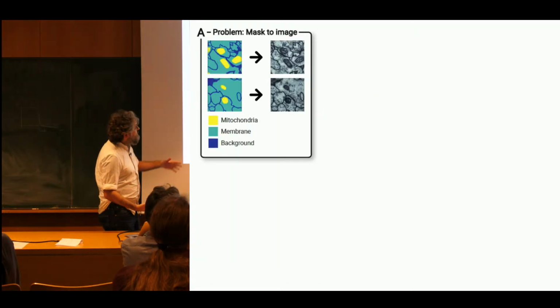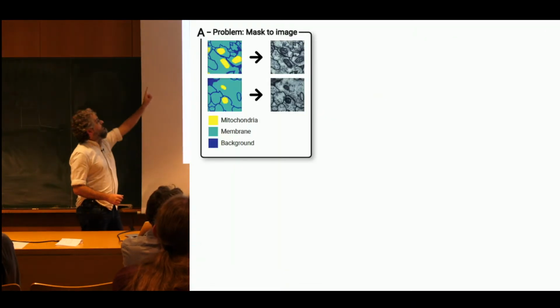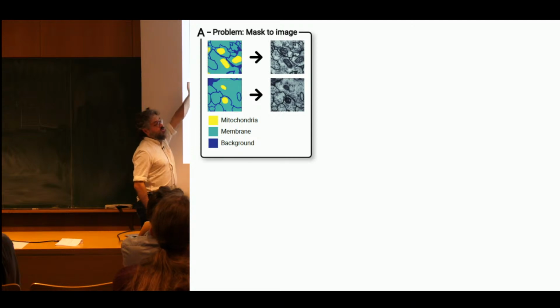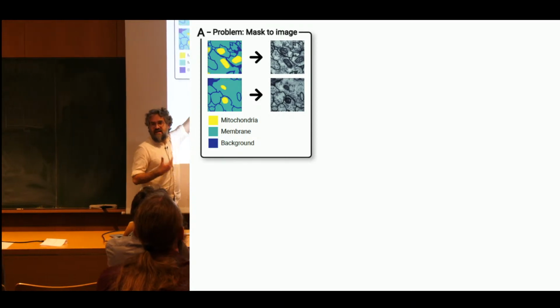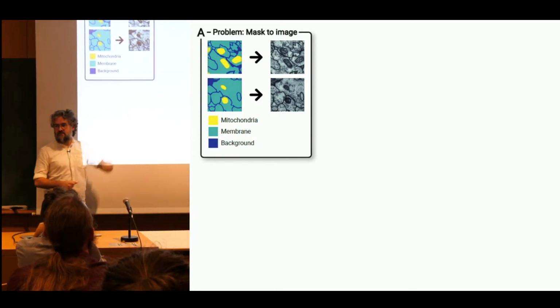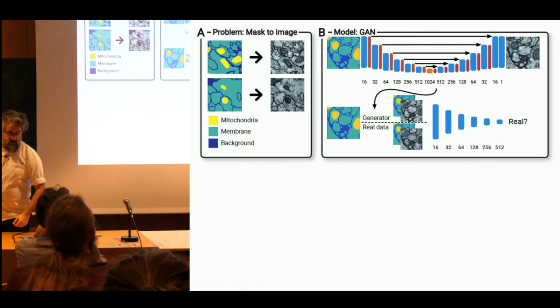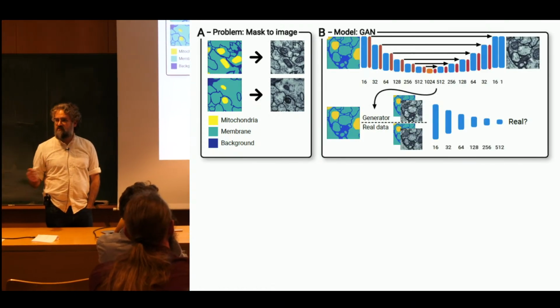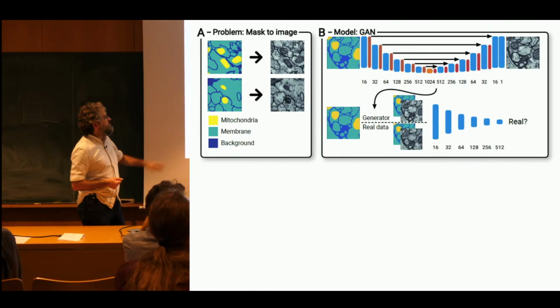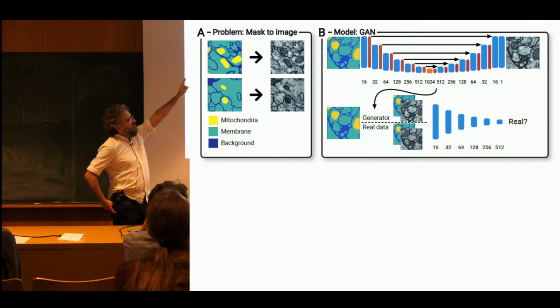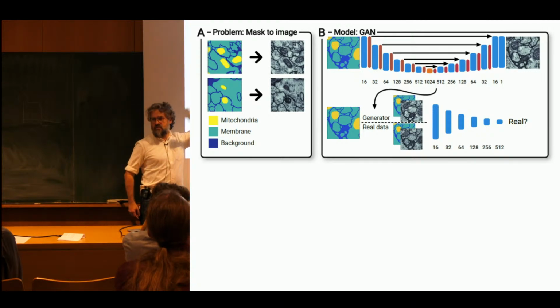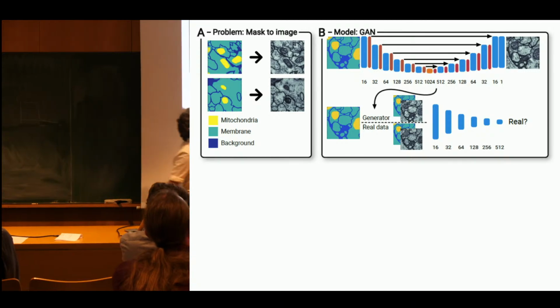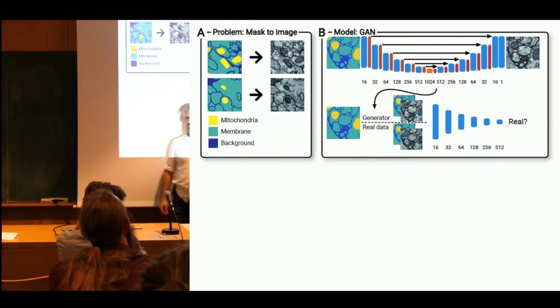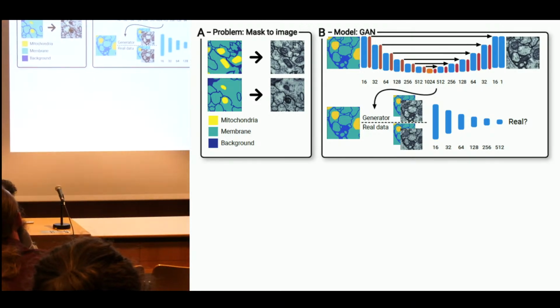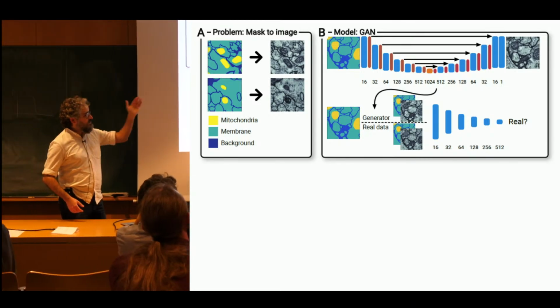Another example that might be interesting is this one, where the idea is to go from a segmented version of a tissue to a tissue that looks like the correct one. And this is done with a GAN, one of these generative adversarial network approaches. Here, what we do essentially is to have a UNet as the generator and a standard discriminator, which is essentially a convolutional neural network, which tells us whether it's real or not.